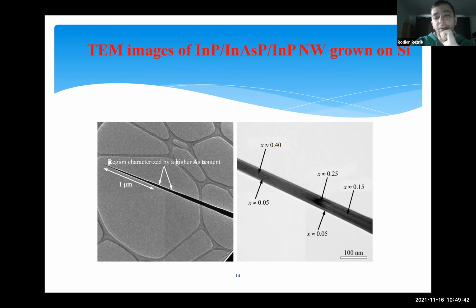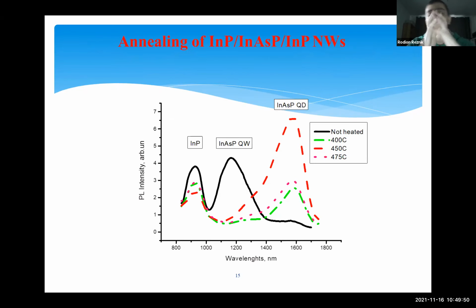It is important to note as well that we have a pure indium phosphide overshell, which is important as well. Then we try to achieve the pure structure with only nanowire and quantum dots, and we try to do it by heating our sample. Here are the different PL spectra after heating the nanowires to 400, 450, 475 degrees. And we can see the peak corresponding to the indium arsenide phosphide quantum well doesn't exist in the spectra beginning from 450 degrees. So possibly the arsenide can evaporate from the nanowires, or go to the quantum dot material.